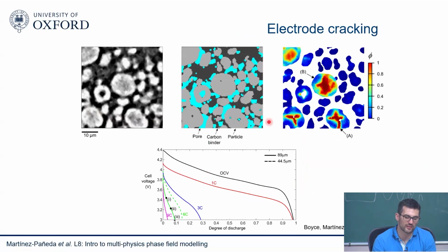The way this works is that you do XCT scans, either in the synchrotron or in a lab XCT. Those XCT scans will normally produce a lot of information, very large files that you need to process. There's multiple ways you can process that. There's a commercial software called Avizo, for example. And then you do some sort of segmentation. There's a lot of people now working in machine learning to speed up this process, but basically you treat those images with whatever tool you want.